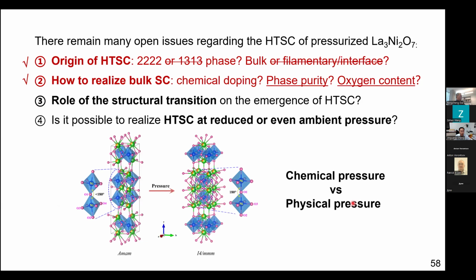Okay, I think at this point, basically, I have answered the first 2 questions. The high TC superconductivity is from the bilayer phase, and you can achieve bulk superconductivity by controlling the phase purity and oxygen content. And in the following, I will quickly go through these 2 parts about the structural transition.